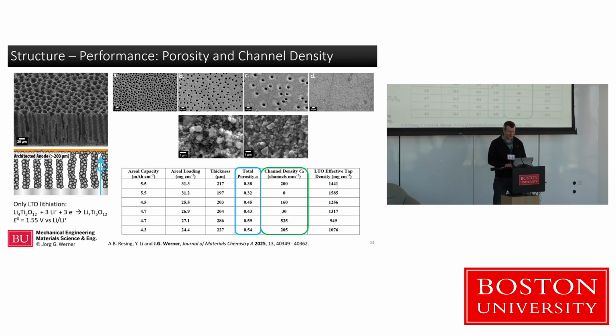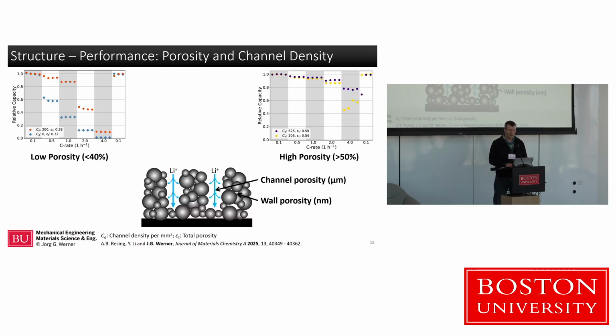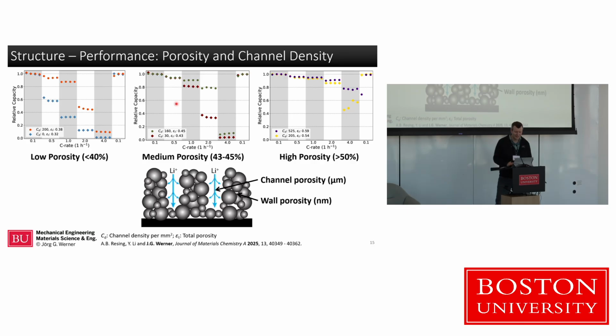These electrodes on the order of 200 micrometers, which is around 3 times thicker than what you currently have in your electrode. We can look at the high porosity end. We see very similar things, but of course, because they have higher porosities, they work well, either of them, low channels, high channels, until you get to the really high rates, like 15-minute charging. And I really like to focus in on this middle one because we were able to make 2 electrodes here that have almost the identical total porosity, 43 and 45%, but one was 30 channels per square millimeter, the other one was 160 channels per square millimeter.